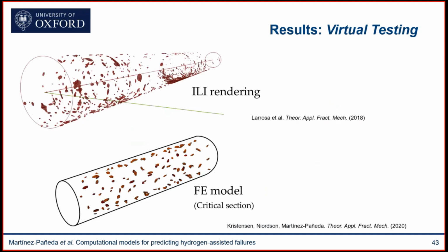And more excitingly, we can correlate this with inspections. So here you see a pipeline. It's a 12-kilometer pipeline that was characterized by Larrosa and co-workers at BP. And this pipeline contains multiple defects. What you see here are hundreds of corrosion defects. These are pit corrosion defects.